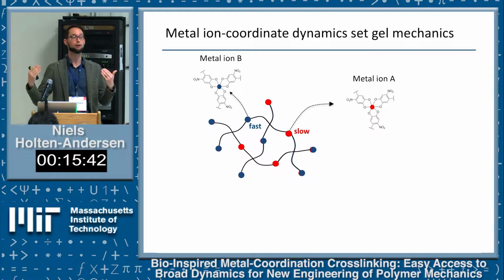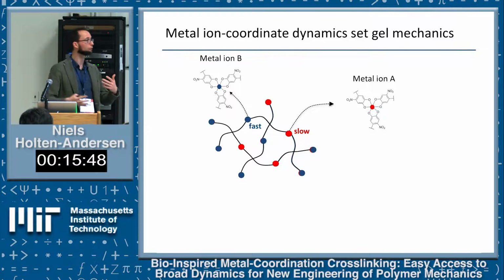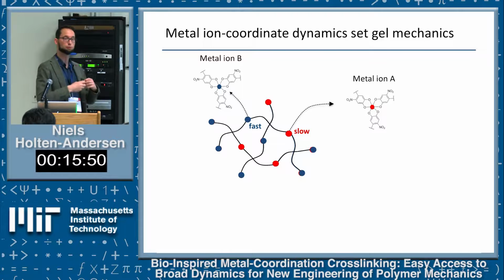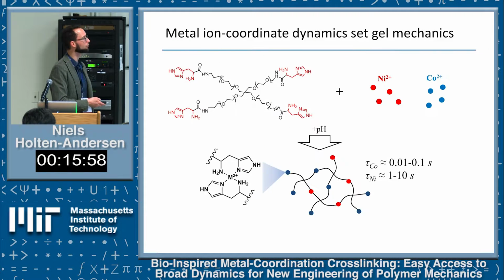This is something that's really hard to engineer with classical polymer engineering, because you typically use molecular weight and you don't get good mixing and so forth. This is super easy in these networks because you just mix in two small metal ions that give you two different time scales in your network. So we have a fast time scale and a slow time scale in the network.